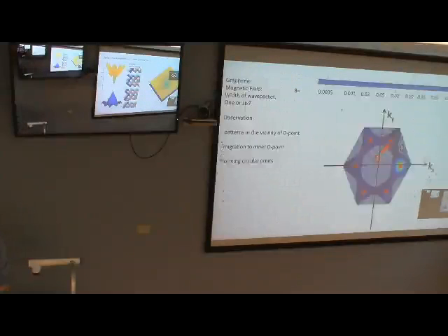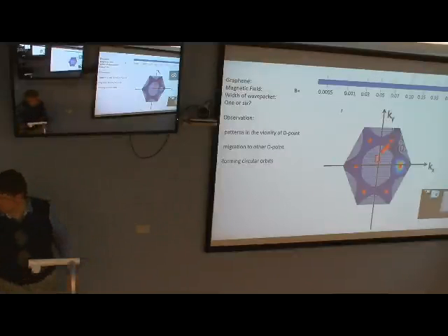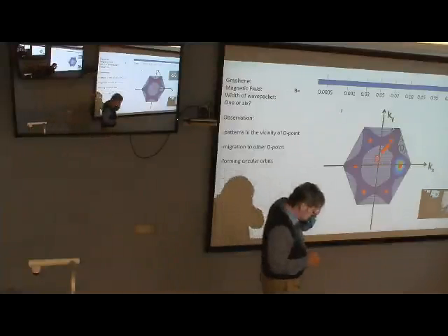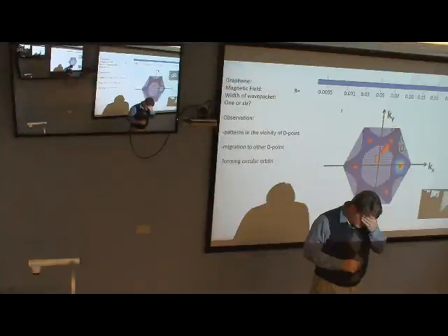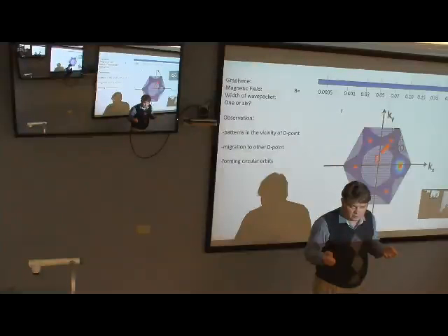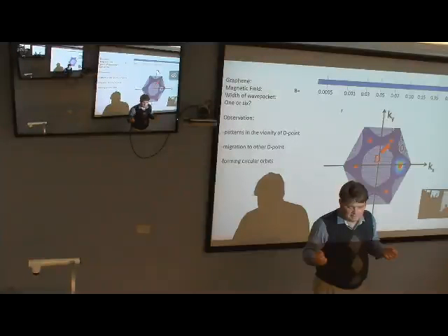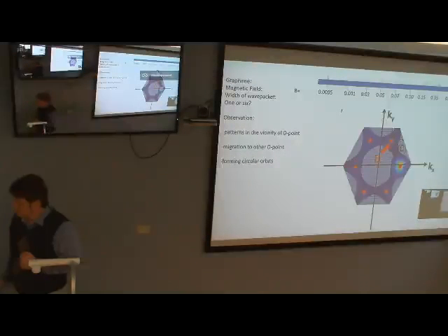the simplest one is graphene. This image is wrong, but the dispersion curve, the dependence of bands on momentum, is very different from free space. Instead of being parabolic, like in free space, they have a conical shape, and for graphene there are 6 of them that are not at zero momentum, but at non-zero momentum values.